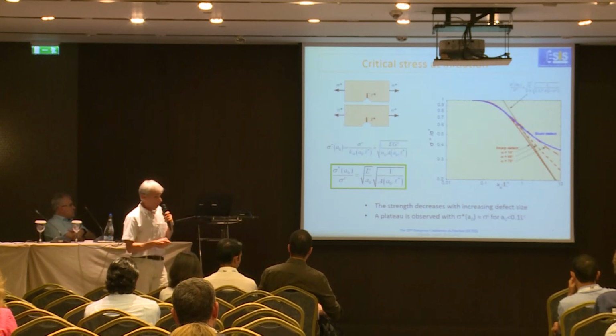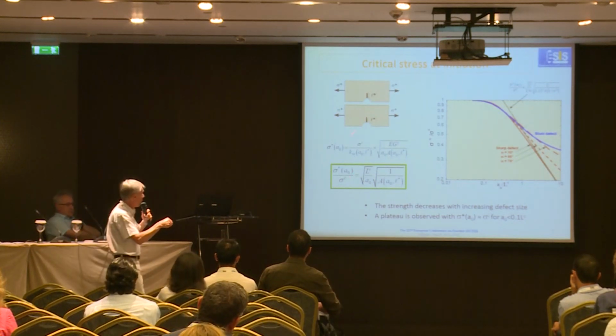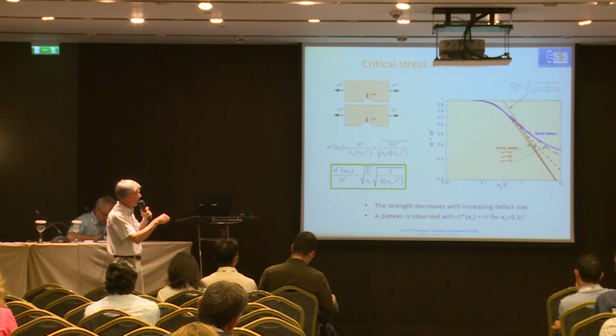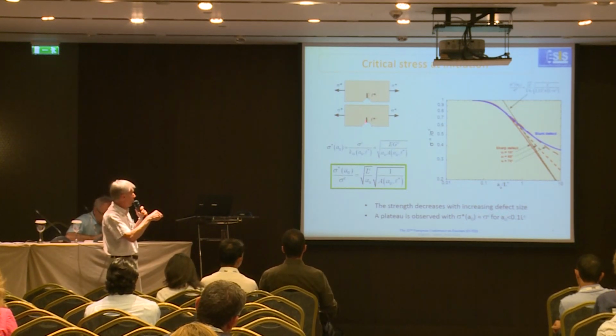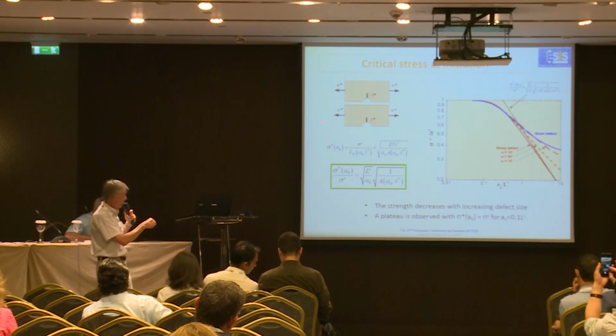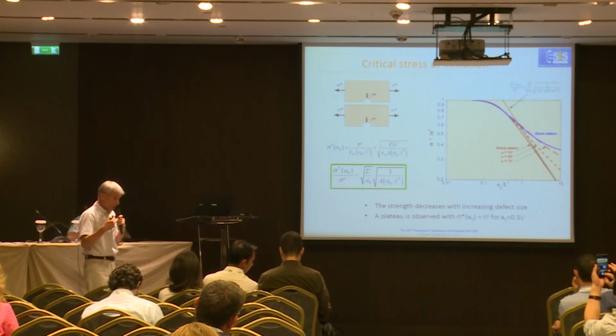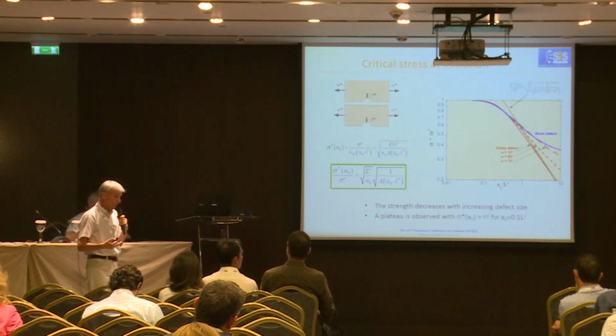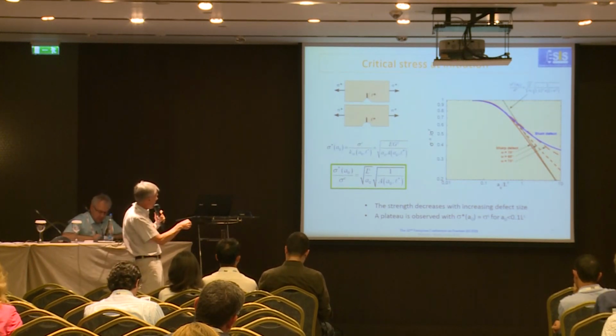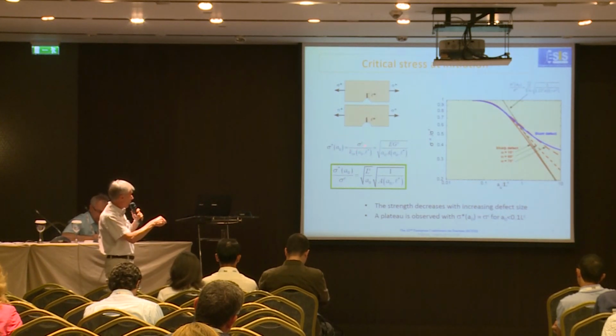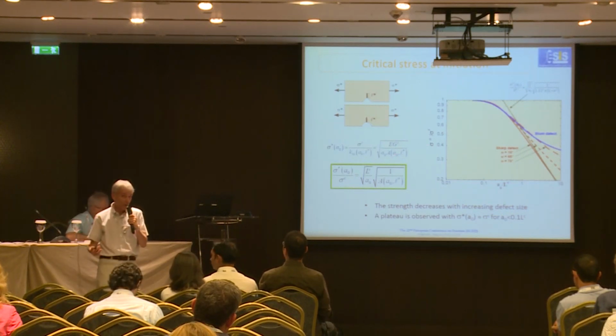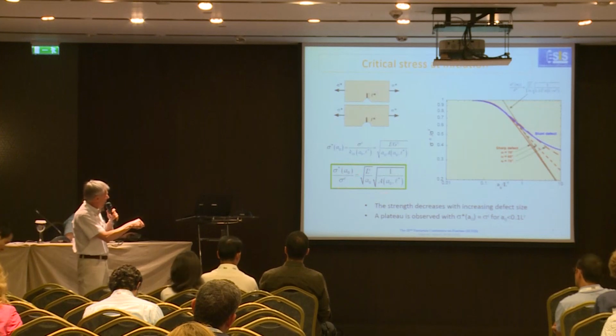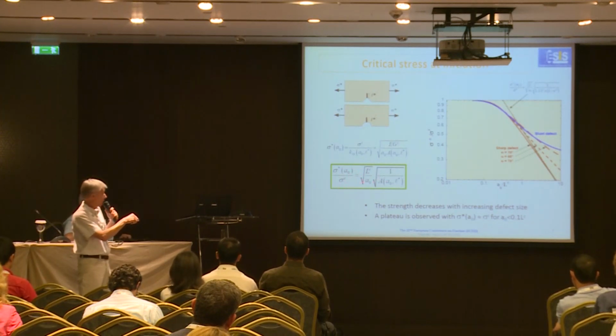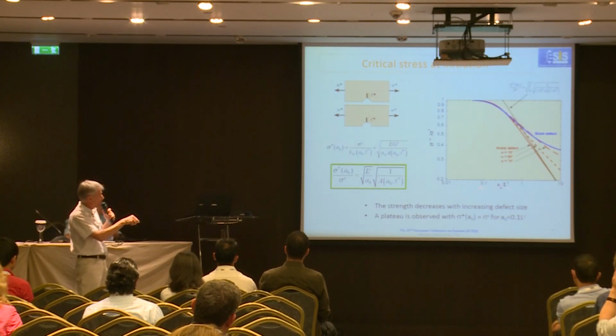Once you have obtained the crack length, you can deduce the critical stress applied to the sample to initiate the crack. This stress will be considered here as the strength of the ceramic material in the presence of the defect. To do this, you can apply either the stress condition or the energy condition. They are fully equivalent. Here I report the stress ratio, which is plotted versus the size of the defect.